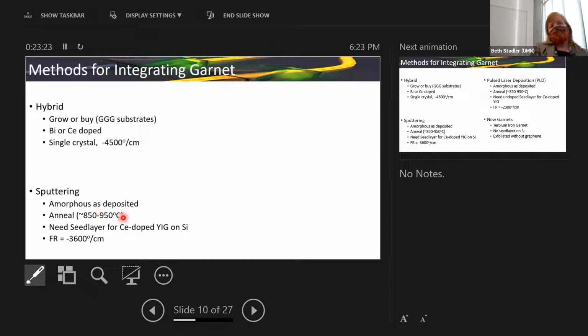It does require an anneal, which is kind of a showstopper for some devices. It means if you're going to put it on top of silicon, you want to anneal it before you put down the laser or anything else. Kind of like the nitrides—I guess if you have to anneal that anyway, anneal your garnet while you're at it, and maybe it won't matter. But you do need a seed layer for the common cerium-doped YIG.